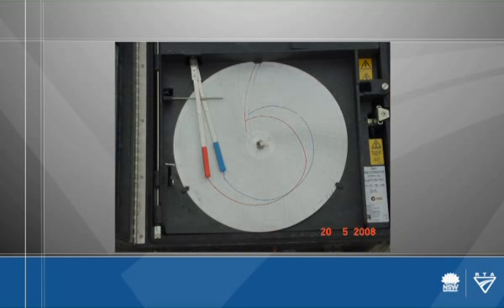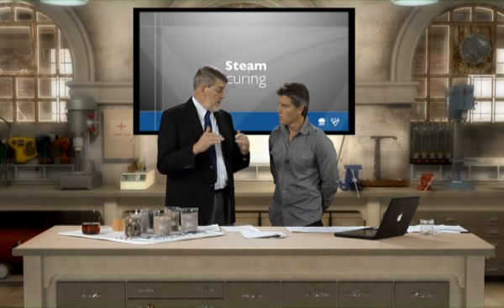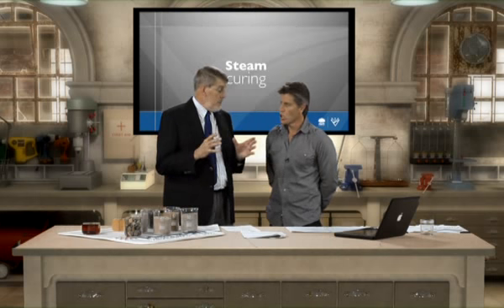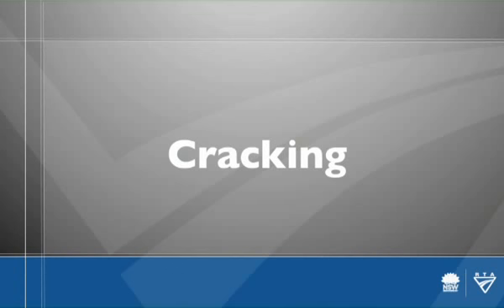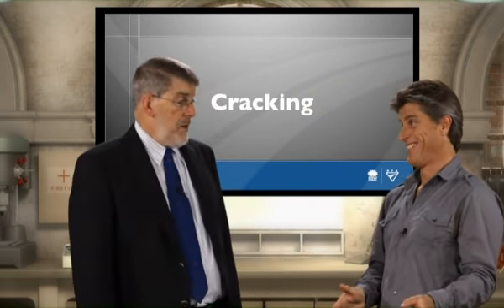So the temperature has to be controlled, the rate of rise of the temperature has to be controlled, and the maximum temperature has to be controlled. It's very critical that these constraints are controlled because steam can actually damage concrete. So that brings us to the end of the 5 Cs, but what happens when we don't follow the 5 Cs? Cracking. Certainly, Peter, and that's what we're all trying to avoid.